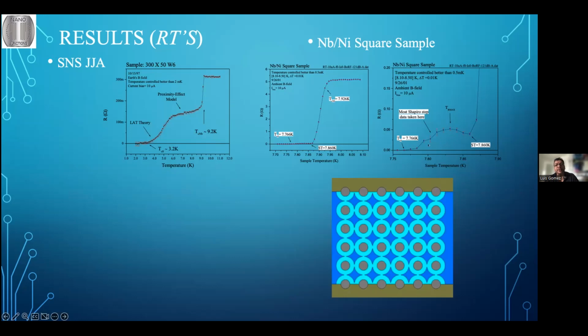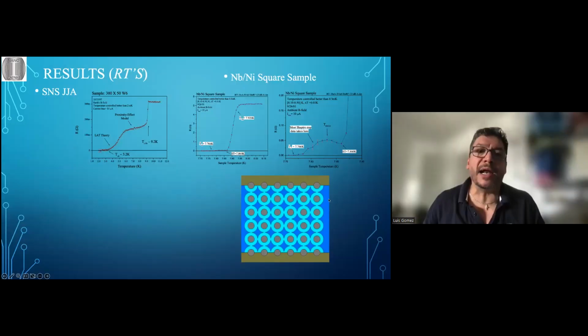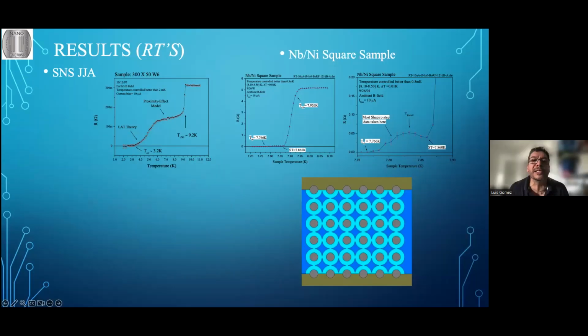So at a temperature around this region, farther away from the nickel, the sample is fully superconducting. So there is this darker blue. We are at a temperature somewhere in between 7.8 kelvins and 7.7 kelvins. So that's way below the niobium transition. So we believe that the niobium film everywhere is superconducting.